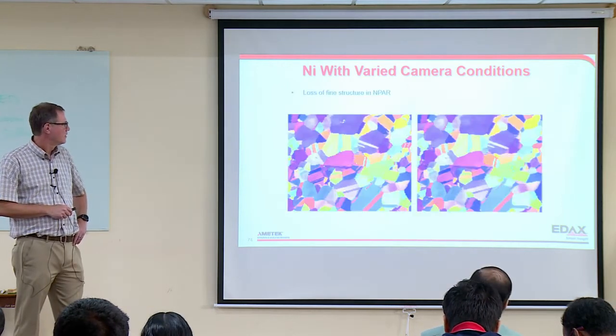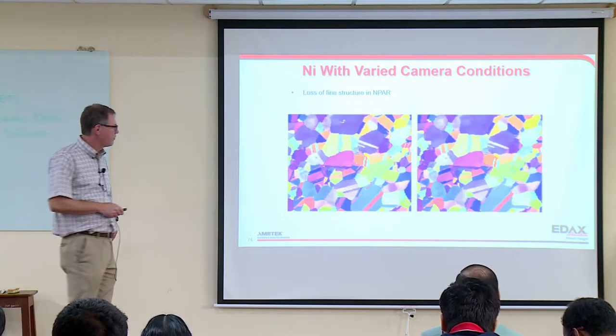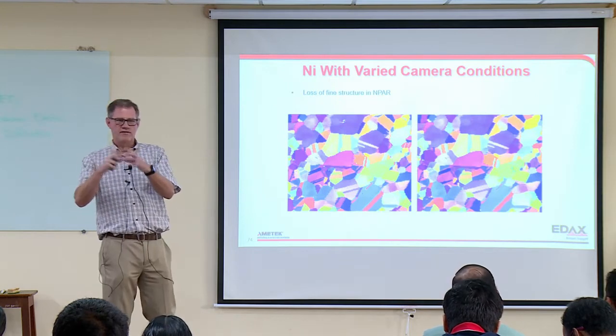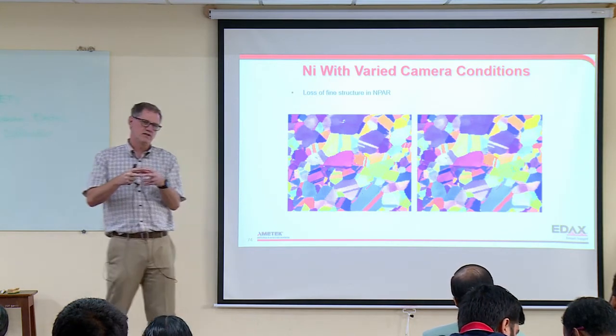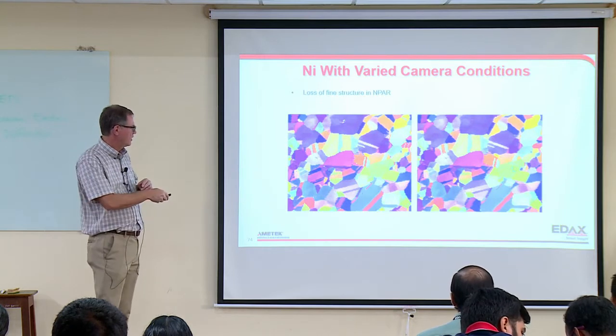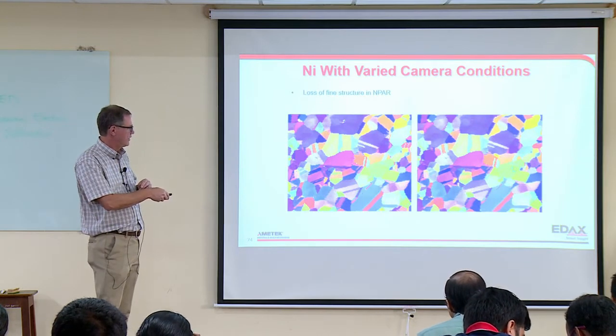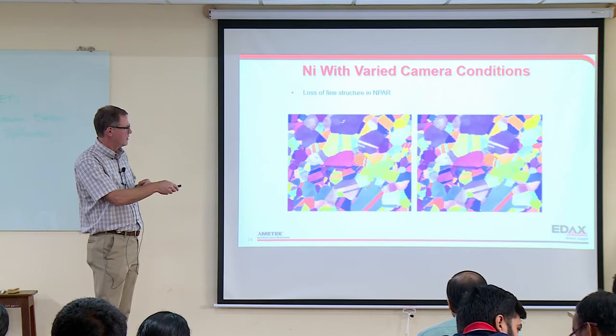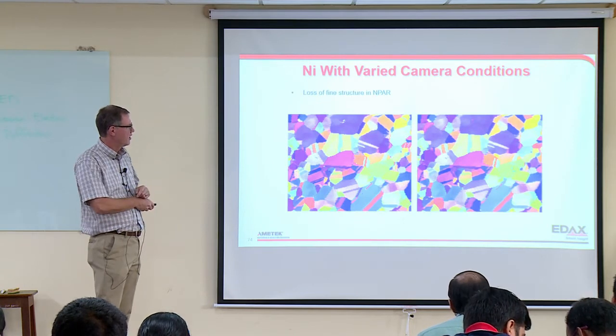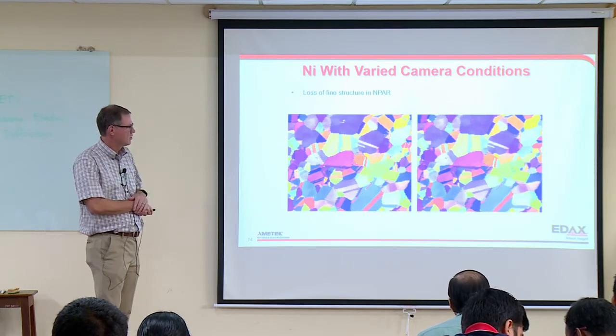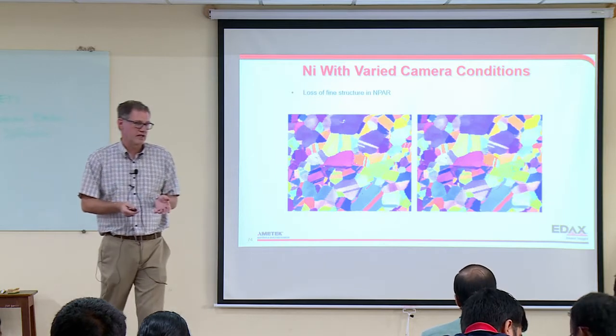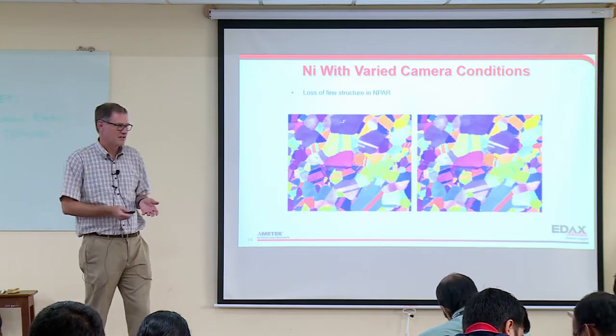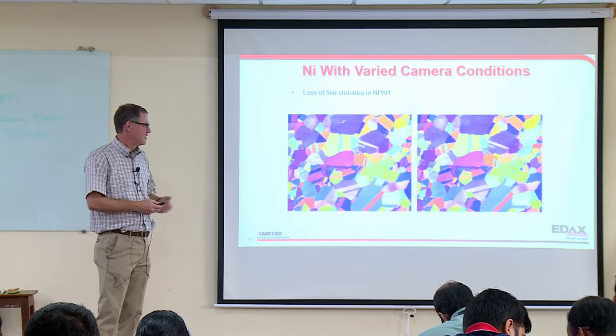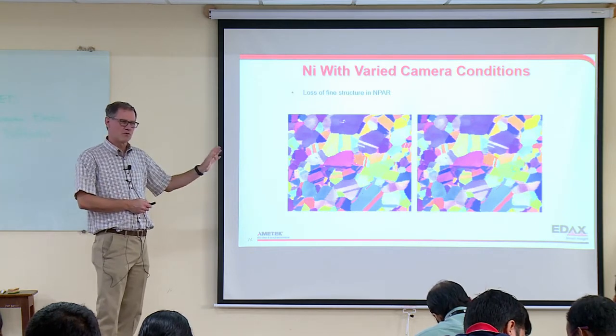But one of the weaknesses of NPAR is we're taking 6 pixels, we're averaging the pattern, so we're going to lose fine details in the structure. And so if you look here at these 2 twins, they get smeared into one. Those 2 get lost. It's completely gone. That one gets lost. So it's especially problematic with twins, actually. It's the worst situation for this technique. And of course, we always do our first examples on nickel, so we saw this right away.